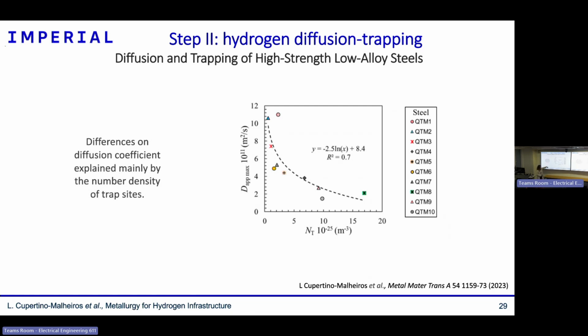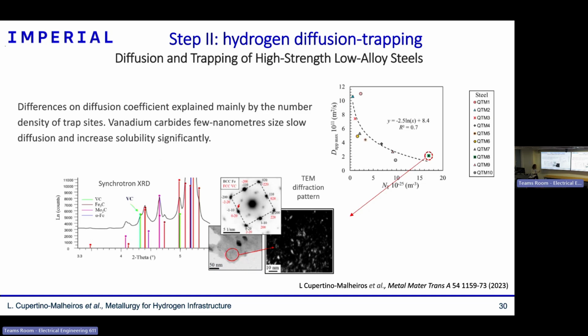And here you can see a correlation between the diffusion kinetics of all these 10 steels and the number of trapping sites. And among all these steels, the one that has a little bit more vanadium was the one with the slowest hydrogen diffusion kinetics, and that could be associated with a population of few-nanometer vanadium carbides that was identified for this steel using synchrotron XRD and transmission microscopy, that can strongly interact with hydrogen and trap hydrogen.